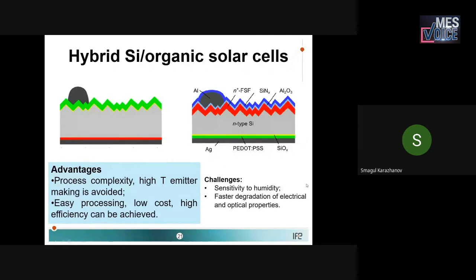So then a hybrid solar cell concept is available now. It combines crystalline silicon with organic material. This solar cell concept came out because of complications in the fabrication of the emitter. The emitter is made, for example, if we have N-type silicon, by diffusion of boron. But doping with boron is a high temperature process, the samples should be heated up at temperatures exceeding 900 degrees C. And at that temperature, silicon's properties will be damaged. And then subsequently, after boron doping, one should clean the surface again, remove some surface layer by HF treatment, which is a time-consuming and energy-consuming process also.